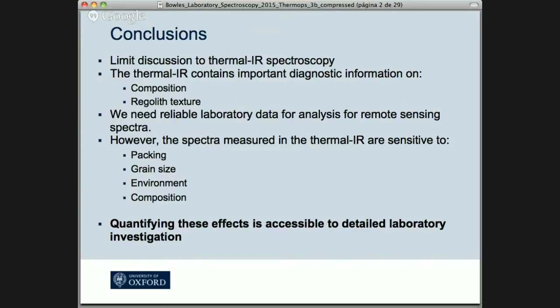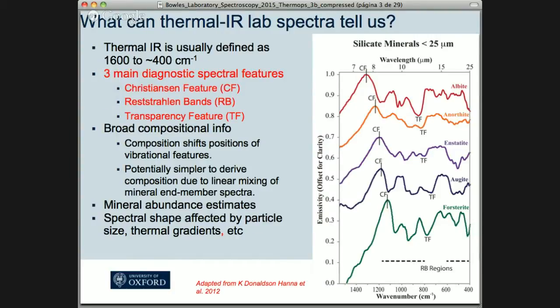So let's look at some fine particulate spectra that have been measured. These are from Kerry Donaldson-Hanna's work, again in my lab, but essentially this is picking out what happens when you have small silicate minerals at very small grain sizes. The important thing to note here is I'm limiting the discussion to 1600 to 400 wave numbers. I use wave numbers because we use FTIR, so that's up to about 25 microns or 20 microns or so. And in this particular spectral region, you've got this hump, which is very characteristic for silicate mineralogy, called the Christiansen feature. You've got the Reststrahlen bands, which are driven by the vibrational silicon-oxygen modes. And then you've got the transparency feature, which is a minimum in reflectance.